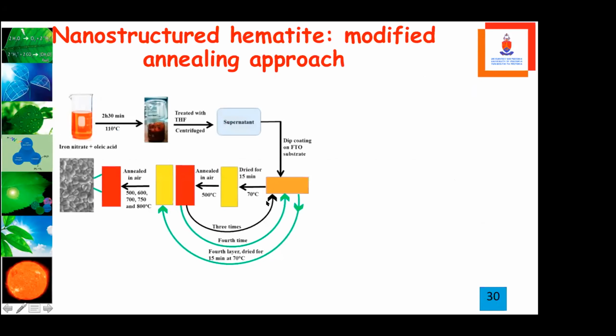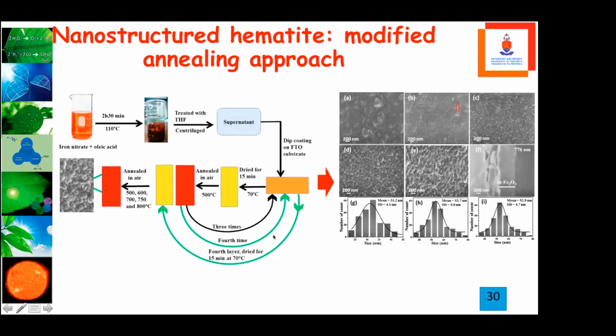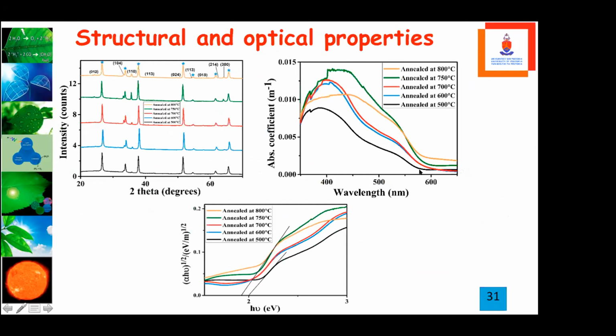The other one was how we made our nanostructures. As you see it here, I just want to rush quickly. And then the pictures here show you that we're able to find the nanostructures with very little diameters, like 31.2 for this material, hematite. And then we did the annealing studies.